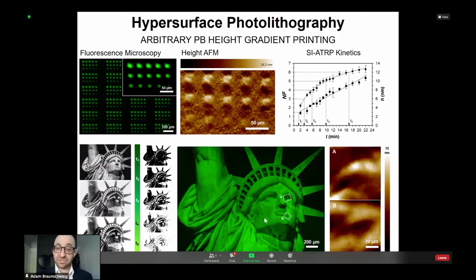Then what we did was we took this picture of the Statue of Liberty, because we're in New York, and we deconvoluted it into 6 different levels of intensity. We loaded the 6 images into our printer, shine light for a different amount of times, and you can see this beautiful image that was generated where the differences in contrast correlate directly to the differences in polymer height, right? And there's no other way to do this without a series of complicated photomasks. And then of course you have resolution issues, but you can do it with photomasks if you want.